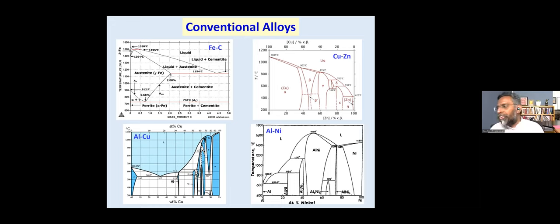And what is common in all these systems, or for that matter any alloy system, is that we usually make alloys which have a very small amount of what is called the second element or the solute element, and a large amount of the solvent element. That basically means in these phase diagrams, we usually operate on one end of the phase diagram. For example, iron carbon alloys: if you think of steels, there is no steel anybody knows with a carbon content greater than 2%. 1.5% or so is the maximum amount of carbon anybody uses, 1.2% or so.